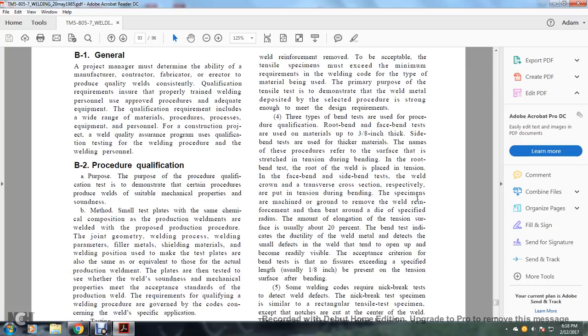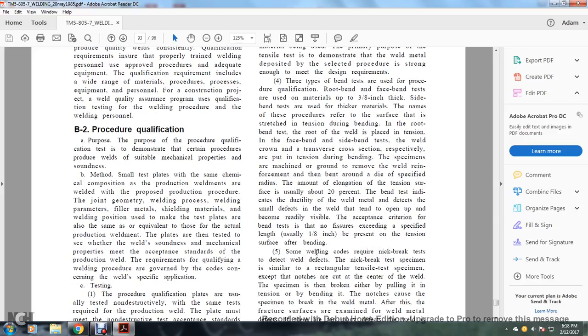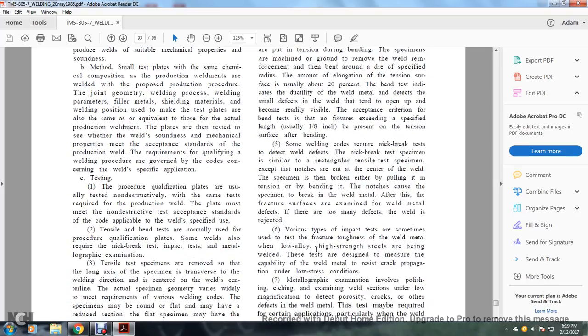Specimens are ground to remove the welding reinforcement and bent around a die that specifies the radius, and the amount of elongation of the tension surface is usually 20%. The bend test indicates the ductility of the weld and metal defects. Small defects in the weld become readily visible. The acceptance criterion for the bend test is that no fissures exceeding a specified length, usually 1/8 of an inch, may be present on the tension surface after bending.